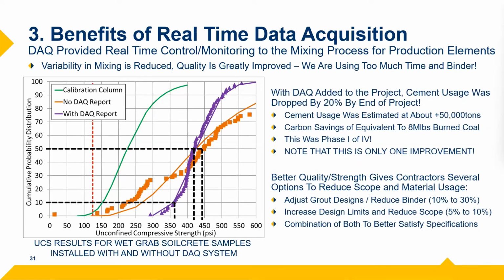So just for this particular project, just with the inclusion of data acquisition on the project, we dropped our binder content by about 20%. So that was a 20% reduction in cement we were using on this phase of the project. When we're talking about projects, phases that are using 50,000 tons of cement or higher, a 20% reduction on each one of those phases is astronomical, really. I mean, we're talking about the equivalent of 8 million pounds of burned coal per phase that we're saving in terms of cement consumption.